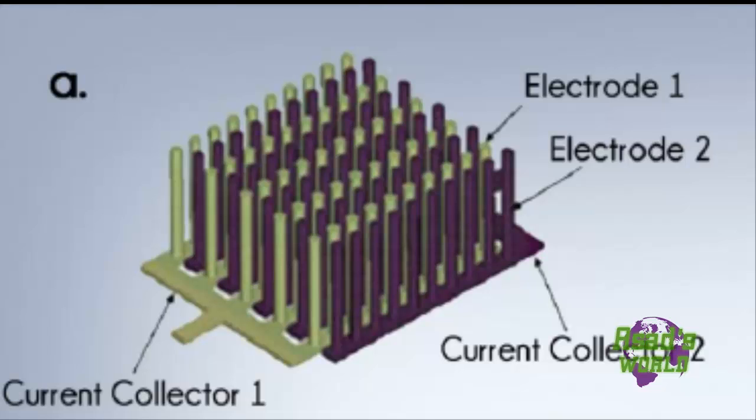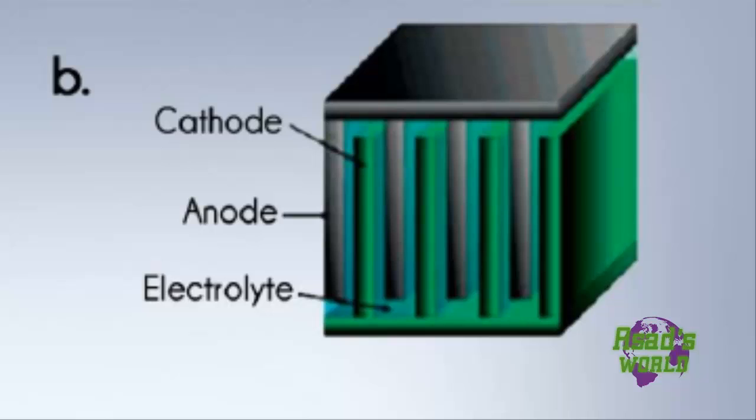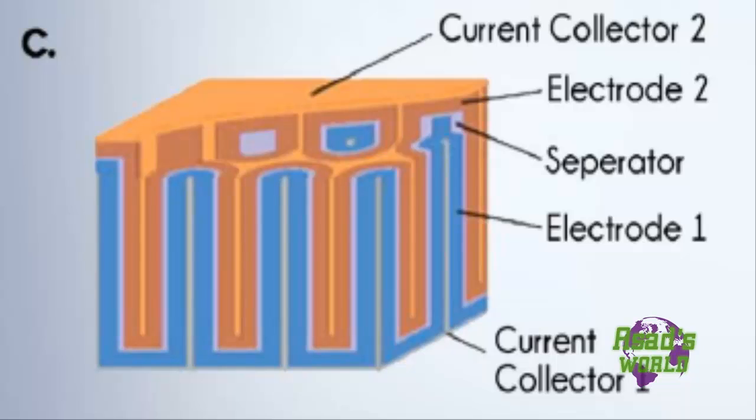years in other devices. The gyroidal thin films of carbon, the battery's anode, generated by block copolymer self-assembly, featured thousands of periodic pores on the order of 40 nanometers wide. These pores were then coated with a 10 nanometer thick electronically insulating but ion-conducting separator through electropolymerization, which by the very nature of the process produces a pinhole-free separation layer.